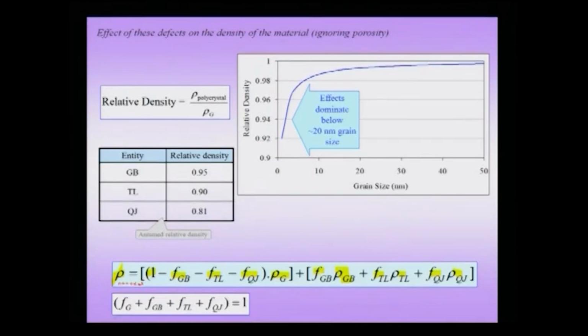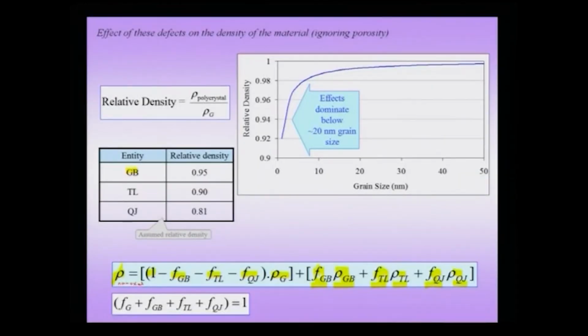Now, to get this number, I need to know the values of FGB, FTL and FQJ. I also need to know the values of rho GB, rho TL and rho QJ. I have already calculated the F's, the volume fractions, in the previous slide. So, I need to know these other entities, and for this, of course, you need to do some detailed modeling, maybe atomistic modeling or molecular dynamics modeling. But a reasonable estimate, arrived at by looking at various models and also experimental results, assumes that the grain boundary density is about 0.95 the density of the grain.